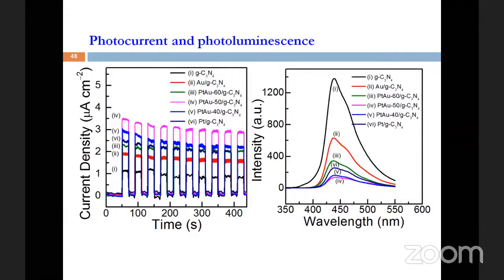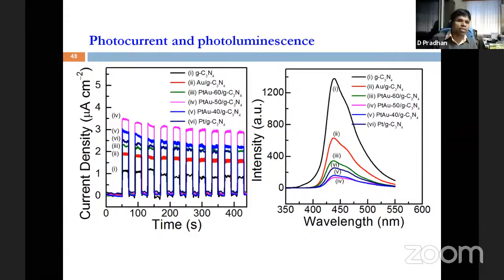Those things have again been confirmed. Electron hole separation was confirmed by photocurrent and photoluminescence measurements, and they matched quite well. When the luminescence is low, that means the recombination is low, and those catalysts gave better performance in hydrogen generation. Theoretically we know that we need to improve charge carrier separation inside the materials to get better performance.